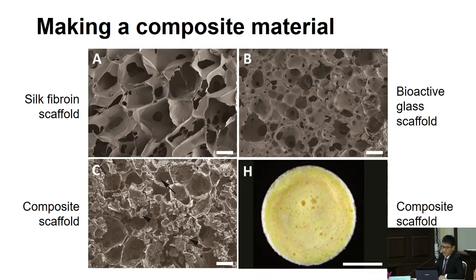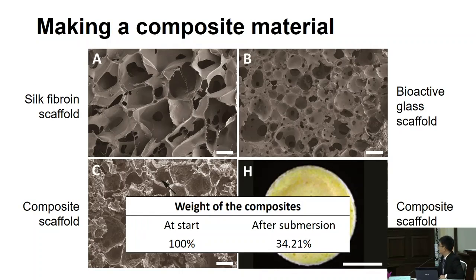But there's still a problem. When we mix them together and got the composite scaffold, we did the same test. We put the composite scaffold in water, and at the start, the mass is 100%. But one day after submersion, we lost about 65% of the weight. So still, this scaffold wouldn't be very practical in the clinic.